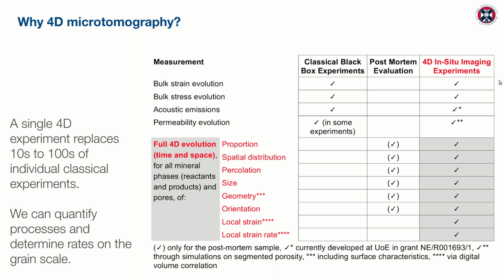However, for the entire experiment, and that's a full 4D evolution in time and space, we can essentially track every single grain. We can track every single grain that reacts, that deforms. We can determine its field state, whatever you want, really. So at the end of the day, we theoretically end up with a vast data set that really tracks the proportion, spatial distribution, percolation, size, geometry, orientation of each individual phase, each individual grain in our sample.